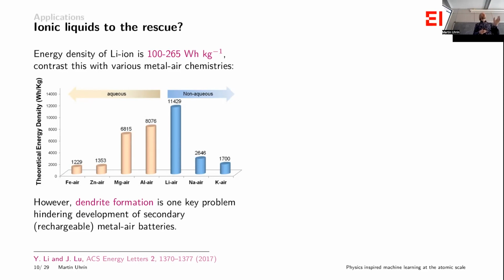You've got your electrolyte and then no cathode. It's just the air, or you've got some matrix that the air can diffuse through your electrolyte and into your anode. And so the energy density of these kinds of batteries is huge because you don't have to count the cathode. In fact, looking at lithium ion, this number is a little bit higher now. You can see, let's say it's 300 watt hours per kilogram. The theoretical maxima, depending on what anode you use, can go up to 11,000, or what I was working on, the zinc air is already an appreciable factor greater than the best lithium